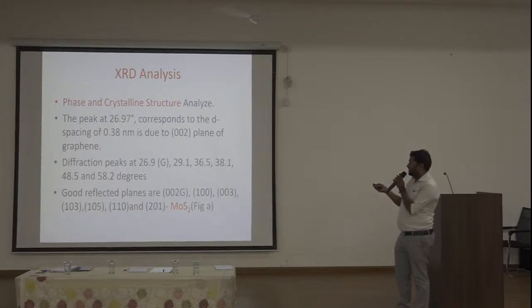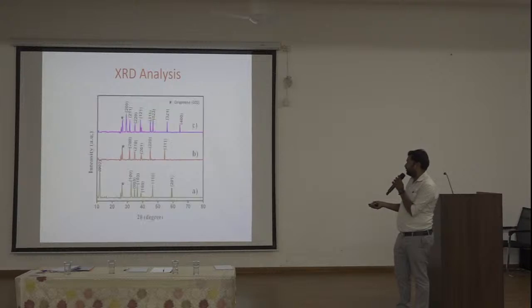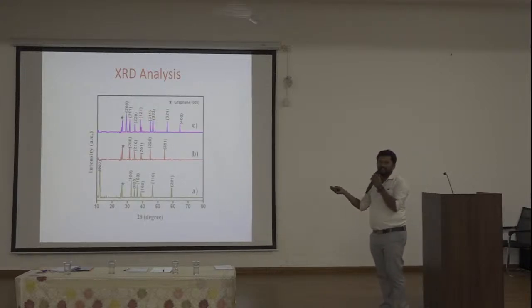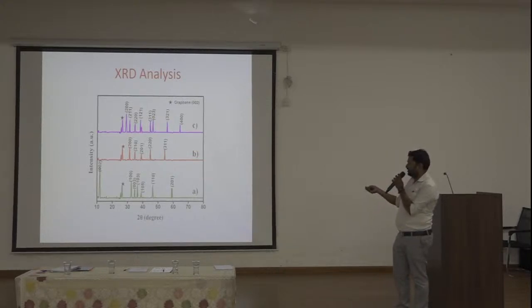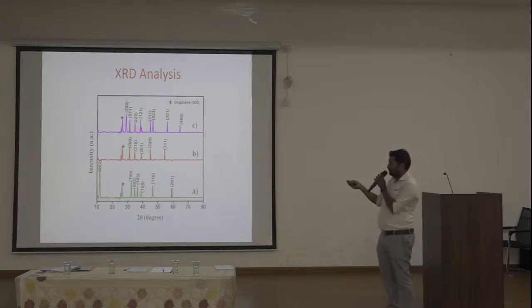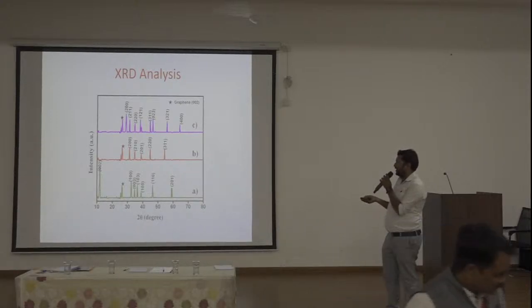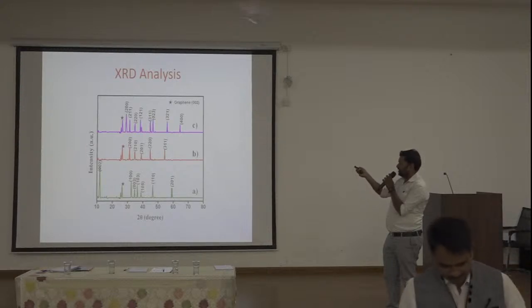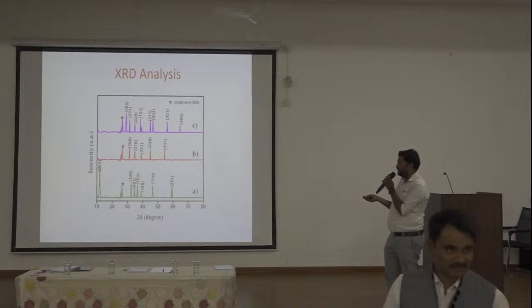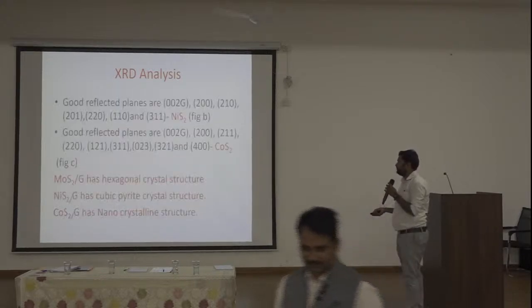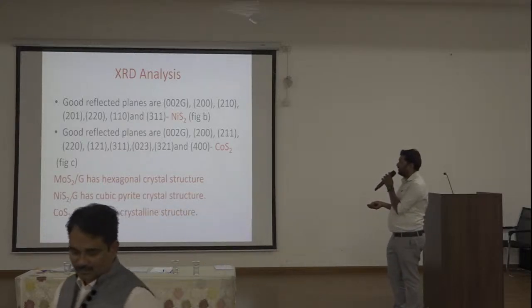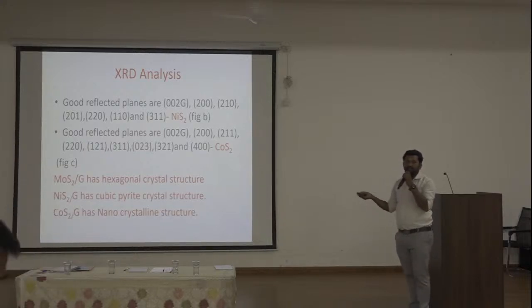In the crystalline structure, the 002 plane is of the graphene, and other planes of the molybdenum disulfide are mentioned here. So these are the different peaks mentioned here, in three different colors. The first one, A, is the molybdenum disulfide, B is the nickel disulfide with the graphene, and C is the cobalt disulfide with the graphene. The 002 plane will indicate the graphene peak, marked with a star, and the other peaks will be the different peaks of the TMDs. So these are the various planes that will be reflected in the XRD analysis of the material.